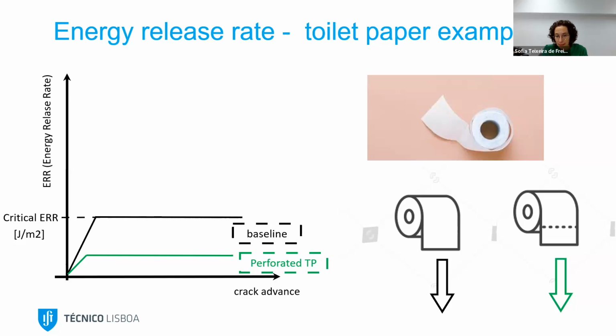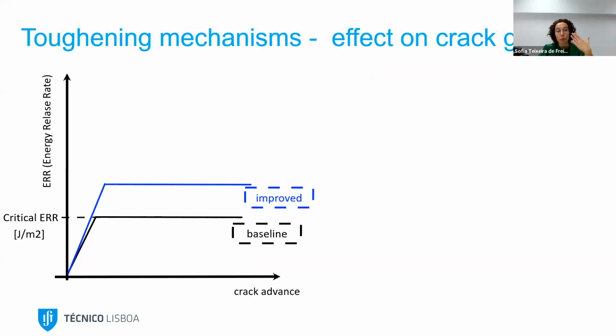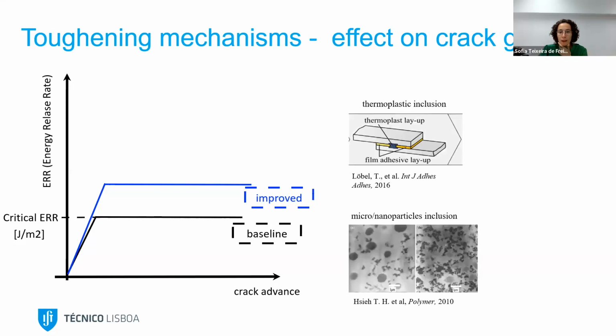So we can apply this simple example also in structures. Well, as you can imagine, in structures we normally don't want to decrease the energy release rate. We want to increase the energy release rate. So that's what we try to do. And in literature, there are many things that we can do for polymers. So we want to improve this energy that is necessary to fracture the material. So we can include, for example, in the polymer, thermoplastic inclusions or nanoparticle inclusions that can improve the critical energy release rate of the material.